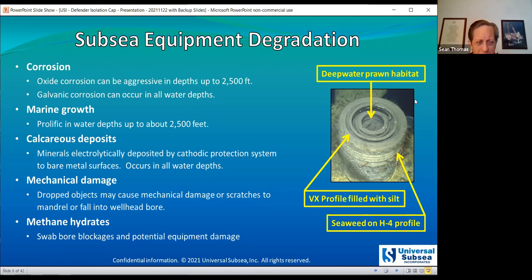Additionally, calcareous deposits are an issue. This is something that's not well understood, and we'll look at that in more detail. These are calcium and magnesium minerals that are electrolytically deposited by the cathodic protection system on any bare metal surfaces, and that will occur in all water depths, deep water and shallow water.